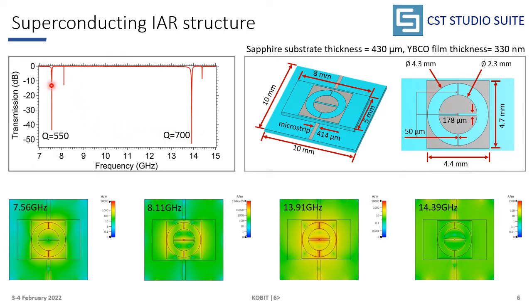And we obtained two main resonant modes, which occur by the coupling with the microstrip. In terms of the quality factors, the first mode has around 550, and the second mode at 14 GHz has 700 in simulations. And we obtained very localized, concentrated microwave magnetic fields around the outer conducting region for the first mode, and for the second mode around 14 GHz we obtained the concentrated microwave magnetic field around the central conducting region.